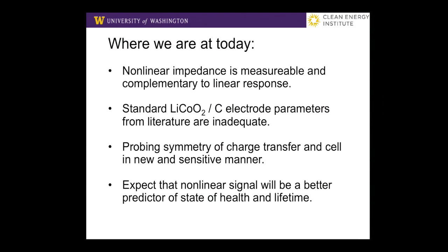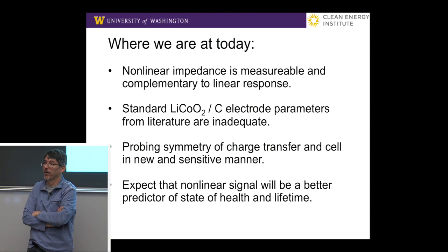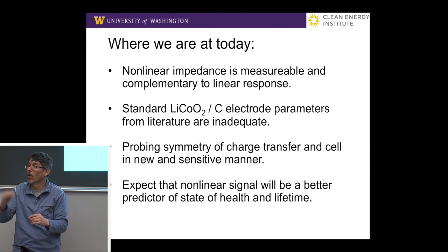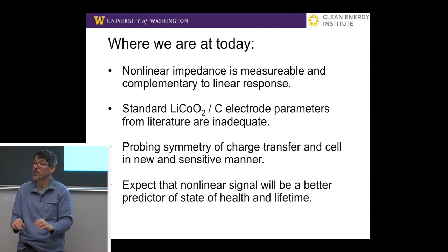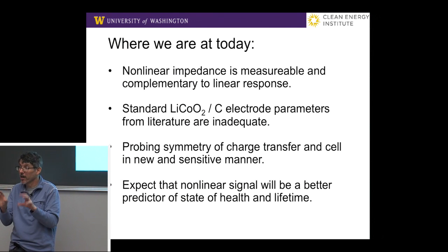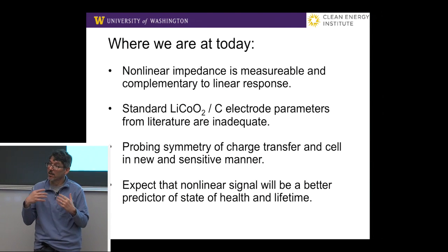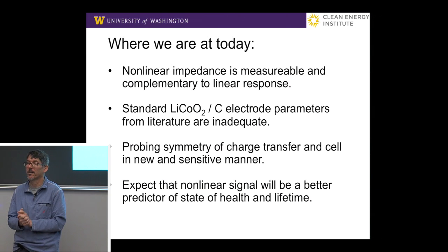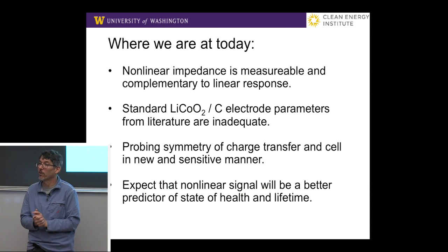So let me just conclude by telling you where we're at today. Nonlinear impedance is clearly measurable, and it is complementary to the linear response. We get information like symmetry out of there. And from that, we can see things like the standard lithium cobalt oxide and carbon electrode parameters from the literature are clearly inadequate when you start looking at the less than 1% of the variance in the data that you can get out from a method like this. We're starting to probe new physics. And that especially hits you over the head when you look at the symmetry of charge transfer as something that is going to be a new thing.